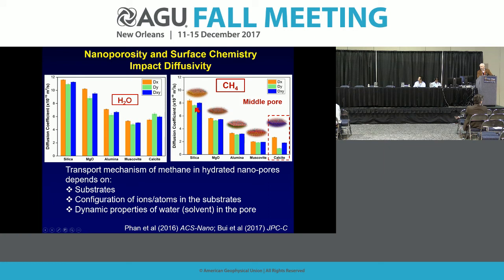As we look at methane within a water-filled pore, we also see this variability in diffusivity, again based on the hydrophobicity of that surface, the structure of water at that surface, and how the fluctuations of water in and out of that surface, as it fluctuates between the pore wall and the interior of the pore, affect solubility. So again, starting to get a sense of the mineralogic control as well as the dimensionality control.